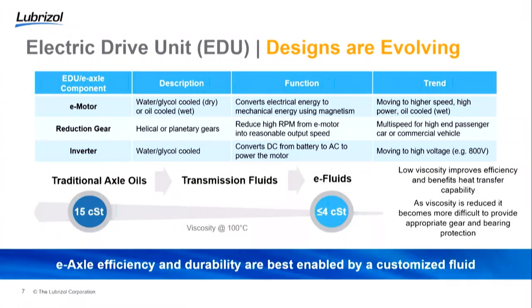I would like to mention viscosity. So for traditional axle oil, think of viscosity at 100 degrees C. Traditional axle oil is typically around 15 centistokes. Transmission fluids can vary between 4 and 7 centistokes in general, but we're seeing with e-fluids those viscosities being down at 4 centistokes or even lower, and that's also due to this need for efficiency.